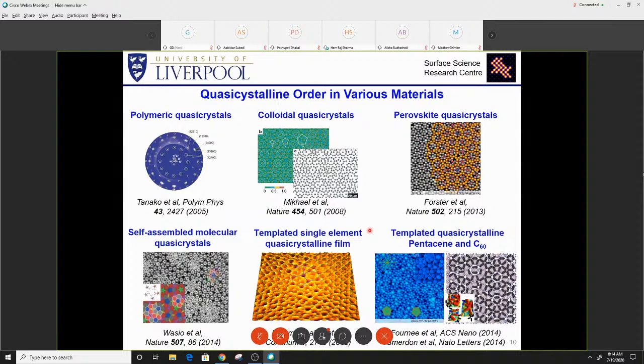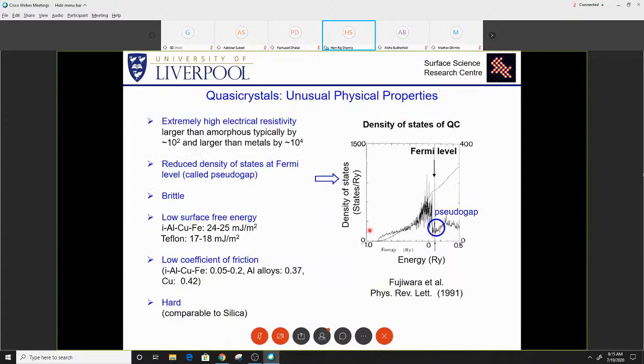So in terms of physical properties, they are metallic alloys, but they have a high electrical resistivity. They have a reduced density of states at the Fermi level compared to usual metals, which we call the pseudogap. They are very brittle compared to ductile metals. They have low surface energy comparable to Teflon, a low coefficient of friction, and are hard materials. Some of these properties are important for technology.